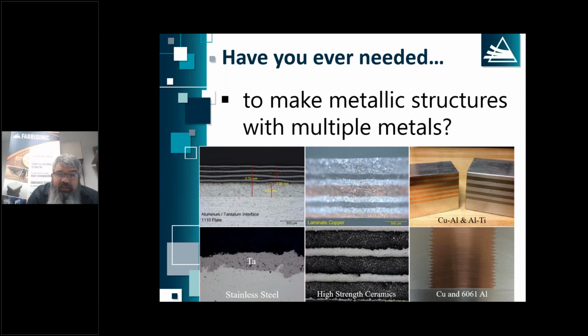Now, one note of caution, certainly if you take these dissimilar laminates and you throw them in salt water, there's corrosion potential there, so you have to still think through the engineering of your products. Similarly, if we take that aluminum and copper and we put that in service at 600C, we're going to start diffusing one into the other and start creating intermetallics. So we still have to use good engineering judgment, but it does give us the ability to kind of put any metal anywhere in the structure that we want.